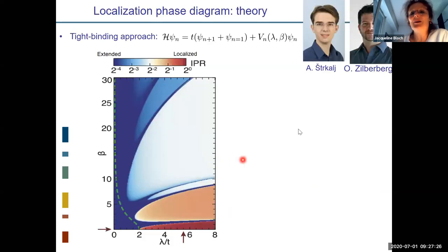So what we did with our colleague is calculate, within a tight-binding approach, what the value of the IPR is when you change lambda and when you change beta. Here you are in the Aubry-André case. Here you are going closer to the Fibonacci. To understand the color, this is the IPR. When it is close to one, you have localized states. So red is localized and blue is more and more extended.